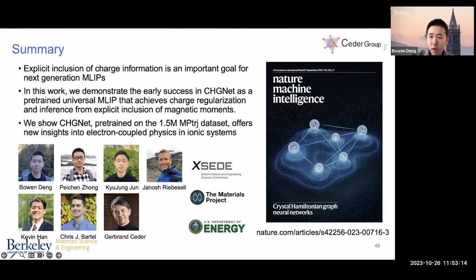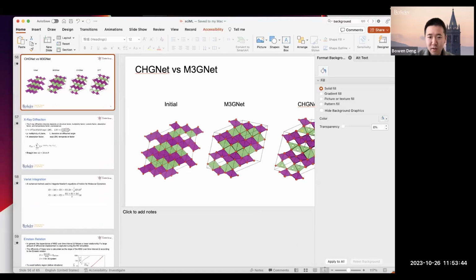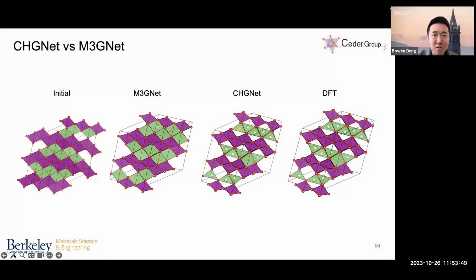So first of all, in a statistical limit, we have found that CHGNet definitely achieves state-of-the-art performance in this new materials discovery task. And if you're looking for specific cases, we found that CHGNet performs better than previous models, which did not include the charge distribution in the formulation of their models. Let me see if I have that in backup slides. Oh, yes. This is a slide that we have tested. This is a lithium manganese oxide cell that we have relaxed with CHGNet, M3GNet, and DFT. On the left is the initial structure, where we removed half of the lithium ions from this lithium manganese oxide cell. We relaxed this with M3GNet, CHGNet, and DFT, and these are the converged structures. Obviously, at a glance, you can see the CHGNet one is closer to the DFT one.